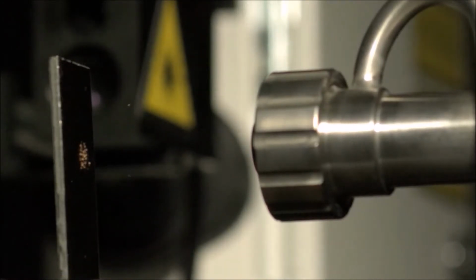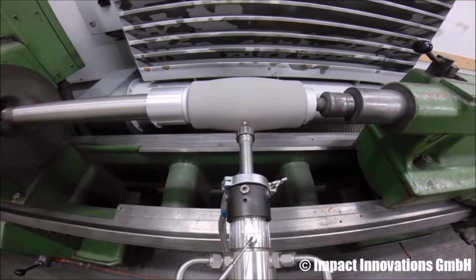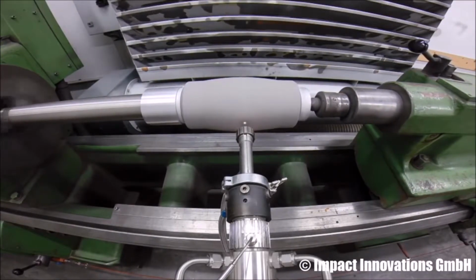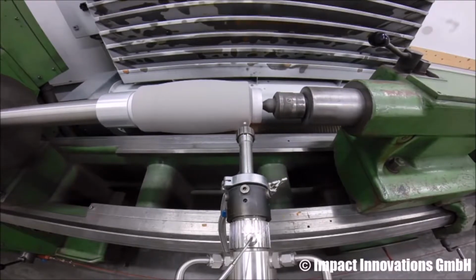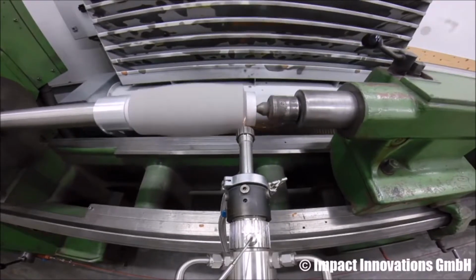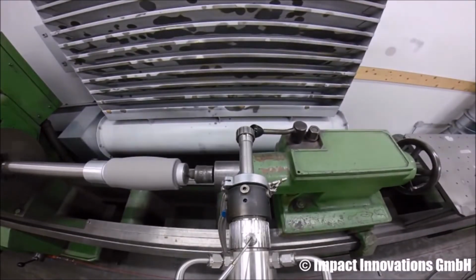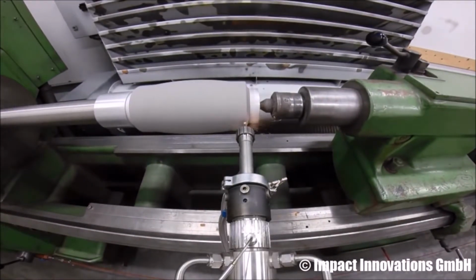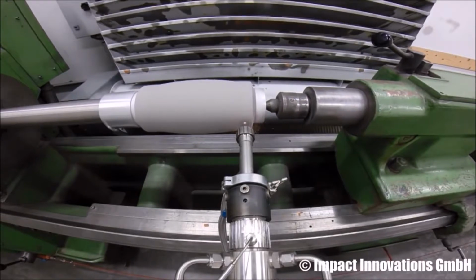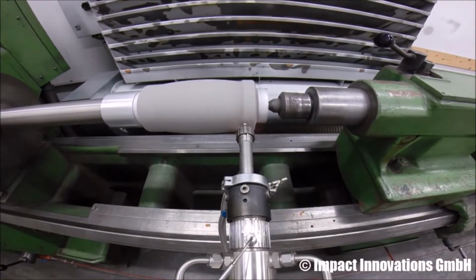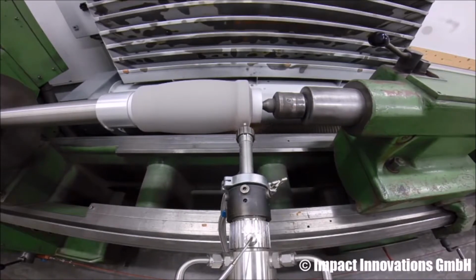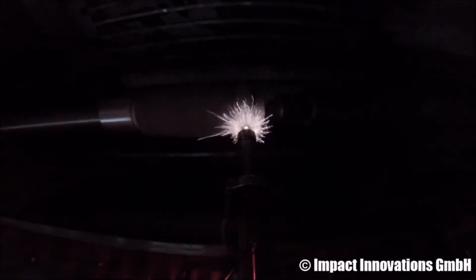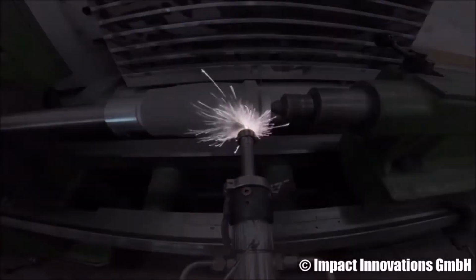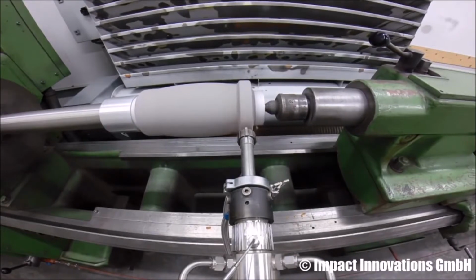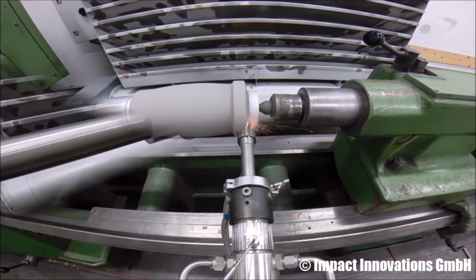When the particles collide with the substrate surface, rapid plastic deformation occurs, disrupting the oxide films on the substrate and particle interface. This in turn creates a strong mechanical bond with low oxide content. The bond is further strengthened due to particles existing in a solid state upon impact, which results in more compressive residual stresses within the bond. Unlike the tensile residual stresses that arise in thermal spray methods, compressive residual stresses enhance recrystallization at the substrate and particle interface. A high rate of recrystallization is indicative of stronger metallurgical bonding compared to that of thermal spray processes.